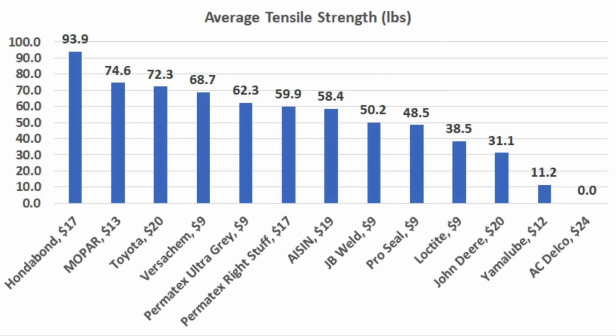If you need a gasket maker with great adhesive and tensile strength properties, the Hondabond came out on top at 93.9 pounds on average. MOPAR finished in second at 74.6, Toyota 72.3, and Versachem 68.7 pounds.